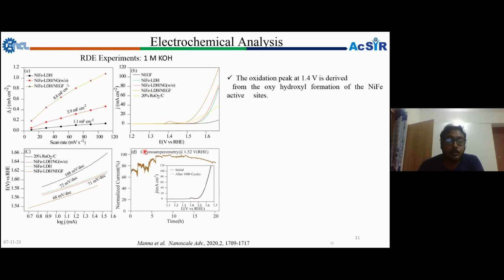So from that we are getting the better value for our predicted catalyst, nickel iron layered double hydroxide supported nitrogen doped graphene. To know the kinetics, we have done the Tafel analysis, the Tafel slope, to measure the kinetics of any particular reaction. Here you can see the nickel iron layered double hydroxide supported nitrogen doped graphene shows the lower Tafel slope value, like 68 millivolt per decade, which means better kinetics compared to the other catalysts. For any electrocatalyst, not only activity, durability is a very good characteristic parameter to know how long it can perform, because activity is a primary factor.